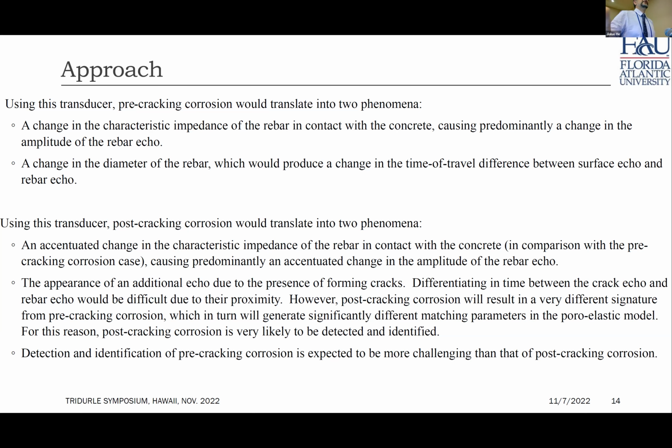The earlier we can spot various signs of cracking, the better it is for people who are doing preventive maintenance and other operations. Now, the idea behind pre-cracking and post-cracking is that we're going to observe changes in the characteristic impedance in the rebar, which is going to be observed in the frequency response of the ultrasonic transmission. And that's what we're going to do right here. We're going to monitor all this.